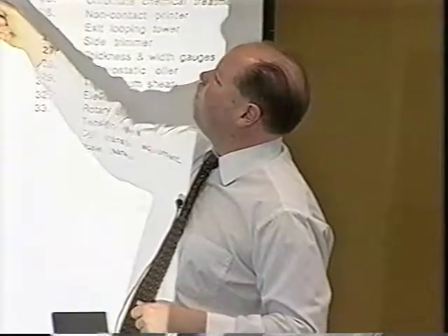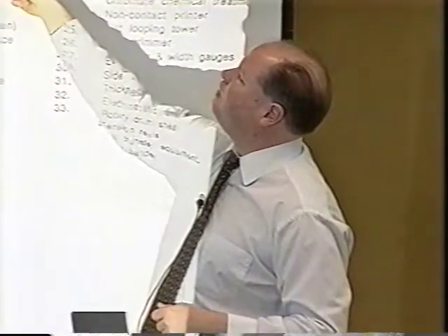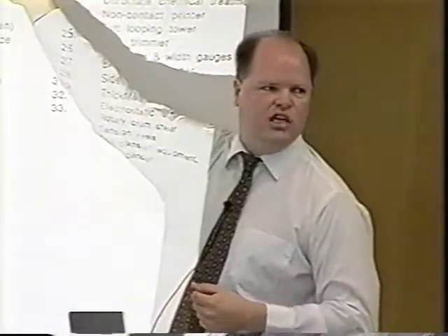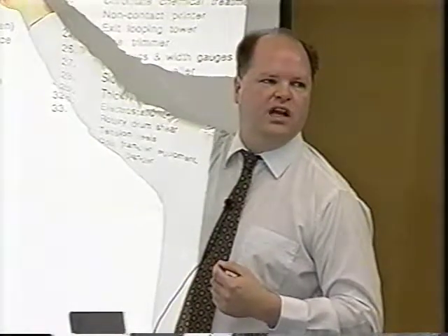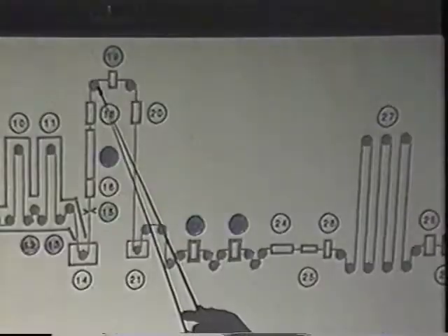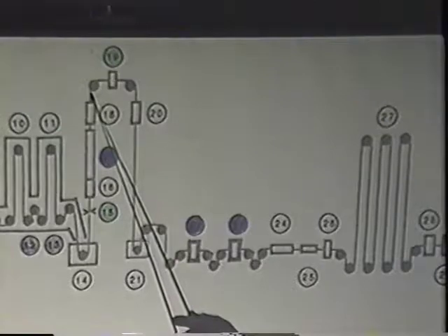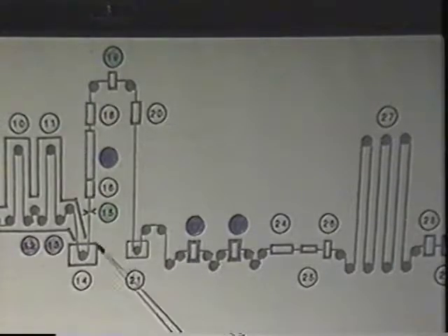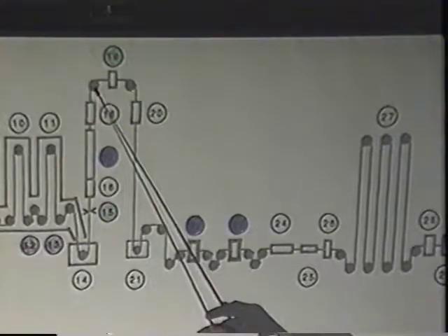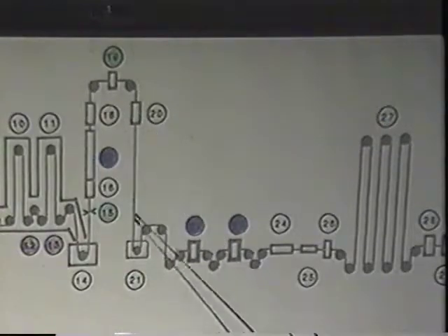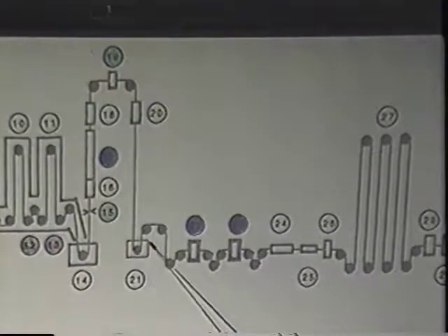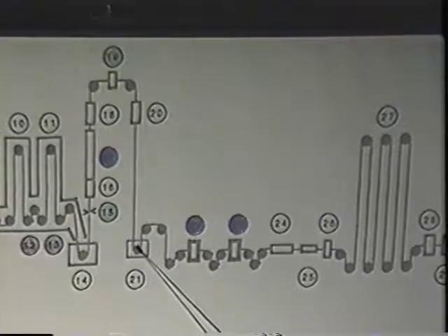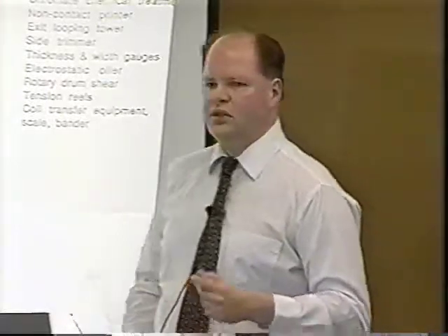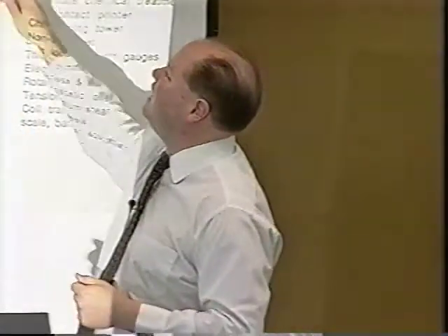So there's like 4 or 5 different cooling zones up through here to cool it down. The strip is about 300 degrees by the time it hits that roll. And this is a water-cooled roll that cools it down even a little bit more. So it's about 860 degrees here, about 300 degrees here. It'll come into the quench tank over here, and that cools it down to about room temperature, maybe 100 degrees or so here in the quench tank. So that's kind of the transitions we're looking at. This would make a nice galvanized product.